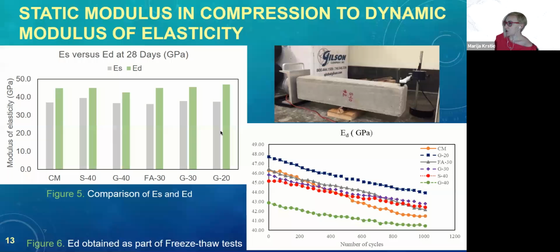Some of the macrostructure evaluations that were performed were static and dynamic modulus of elasticity, and they were compared at 28 days. It is obvious that dynamic modulus is higher than static modulus for various reasons. Some of those reasons are that the geometry of samples was different and the type of load was different. We tested beams that were 16 inches long and 3 by 4 inches in cross section for dynamic modulus.